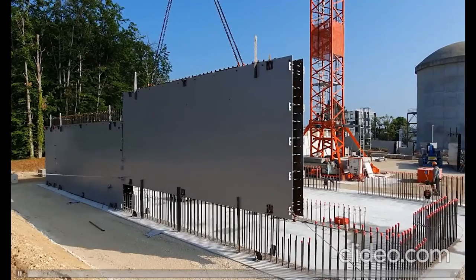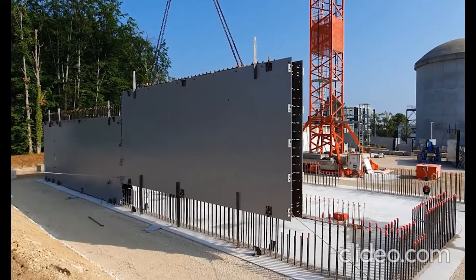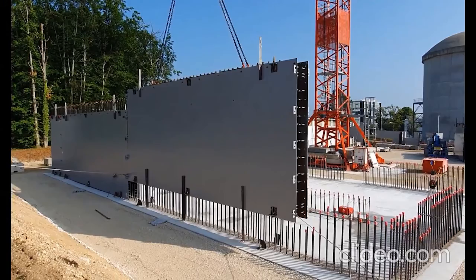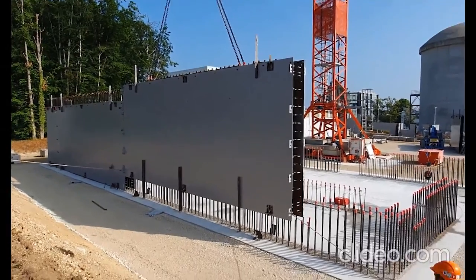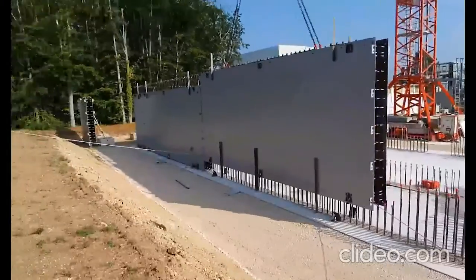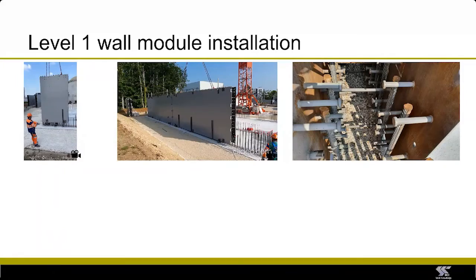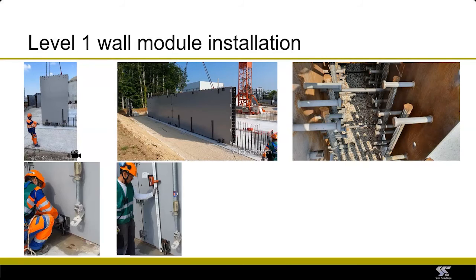And then the next module, again being lowered into position over the starter bars, being pulled against these erection guides that we saw earlier. And you can see why it's important to have the starter bars installed very accurately. You have the plate very close to the starter bar, you have shear studs, you have tie bars. So in order to avoid any clashes, it is very important to coordinate this in the building information model and then to ensure that it is executed correctly on site.